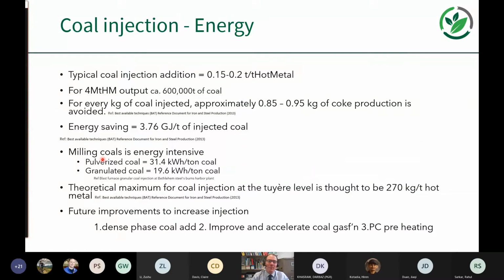But in terms of energy, typically the coal injection additions would be up to a couple of 100 kilograms per ton of hot metal. So for an output of 4 million tons, which would be typical of Port Talbot, we're talking about 600,000 tons of coal. And you substitute that for about 0.95 kilograms of coke. So you avoid that coke production, so you reduce the emissions associated with it. And there's a significant energy saving. Best available technique data quantifies that at 3.76 gigajoules per ton of injecting coal. So there's an energy saving associated with it.